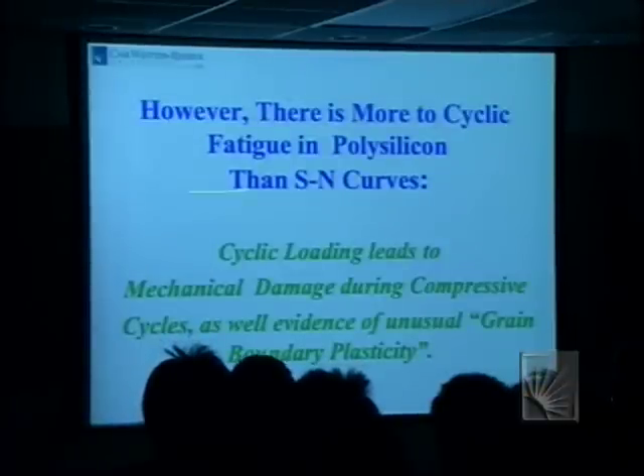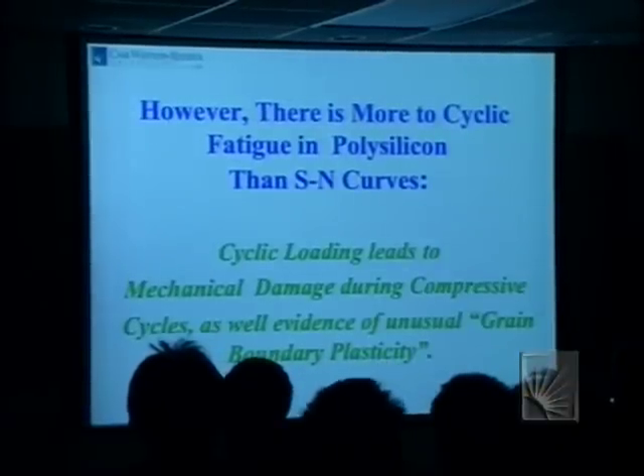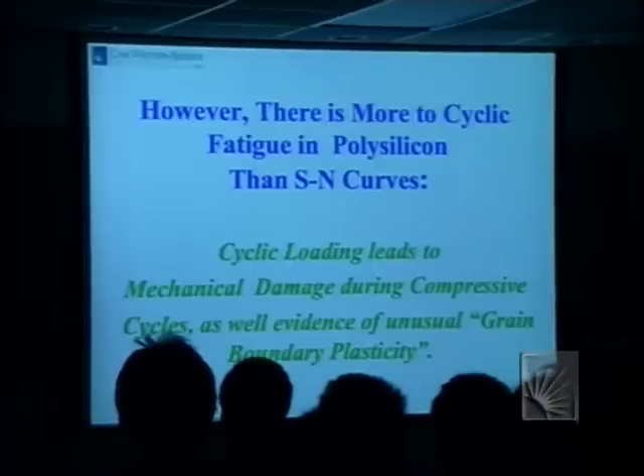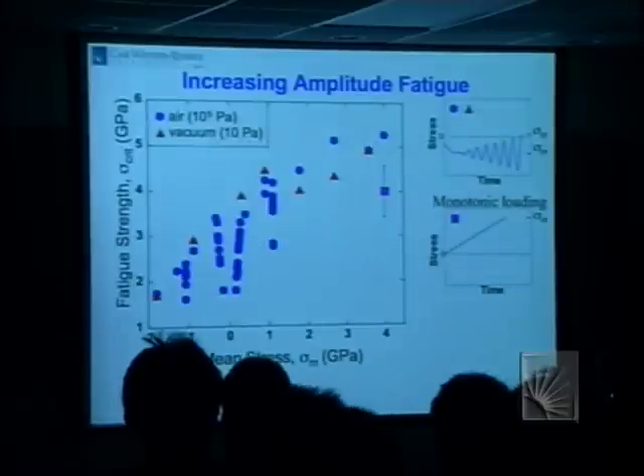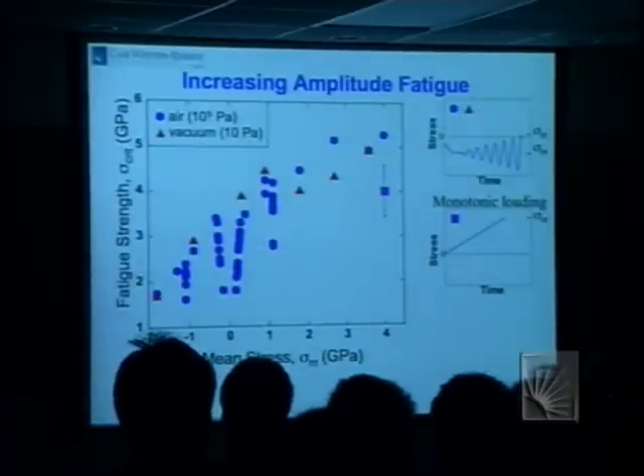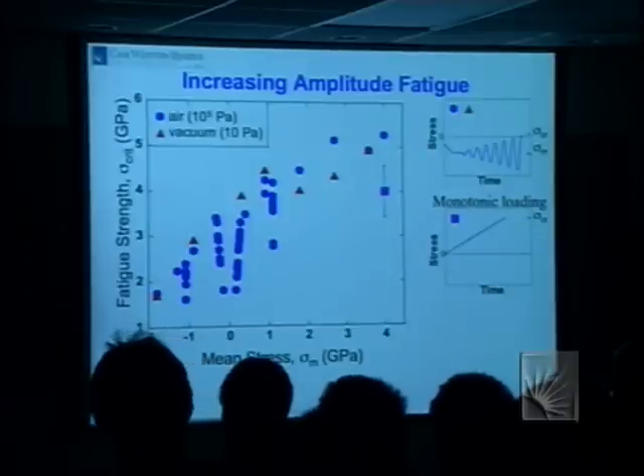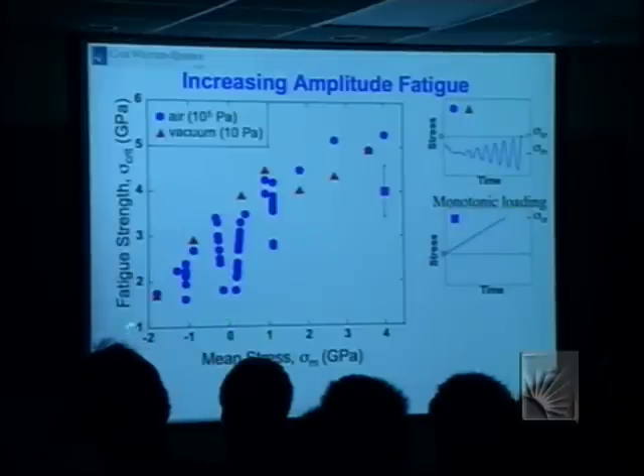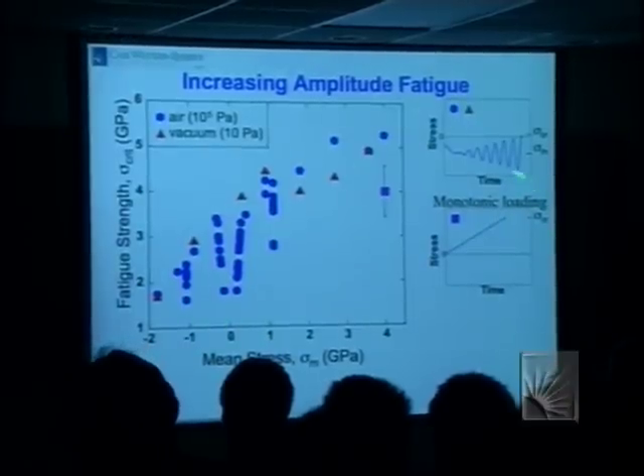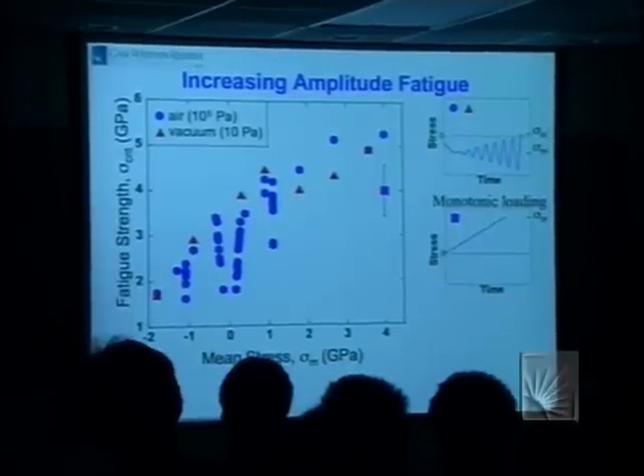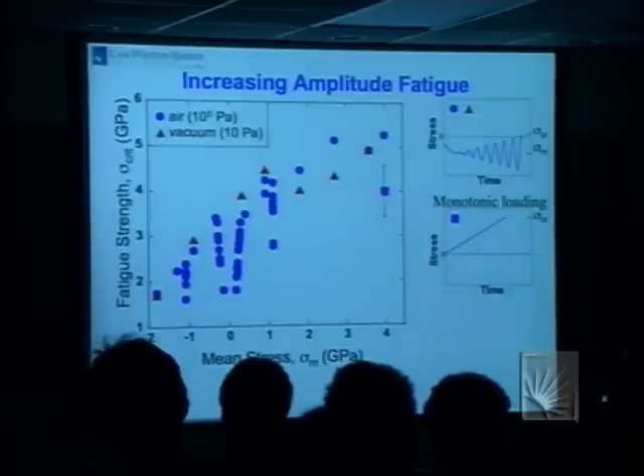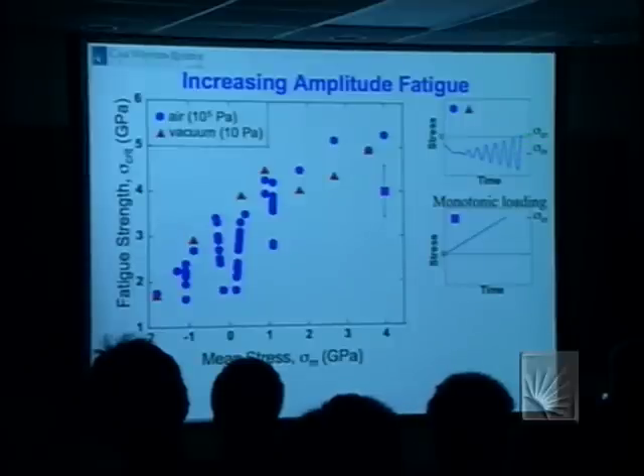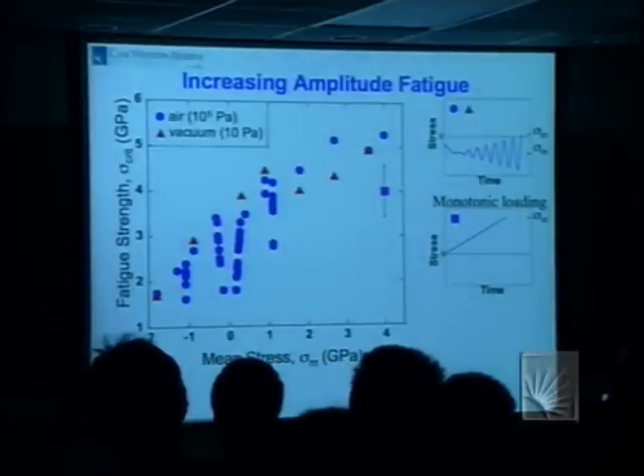Well, there's more to cyclic fatigue than just S-N curves. I'm going to show you further evidence for mechanical damage during these compressive cycles, as well as some unusual grain boundary plasticity. So what we're able to do with our devices is impose mean stresses of varying sign and magnitude. And remember, the way we do this experiment is we impose a mean stress, and then we increase the amplitude of the AC voltage until we get failure. So we impose a DC bias, and then we assume that failure occurred at the maximum of the tensile part of the stress.